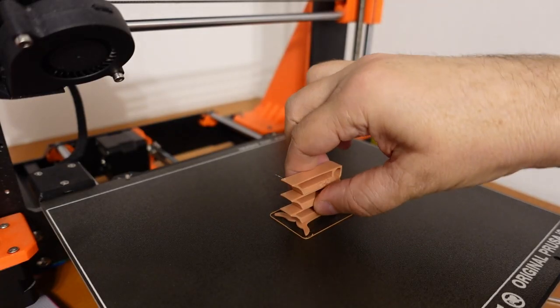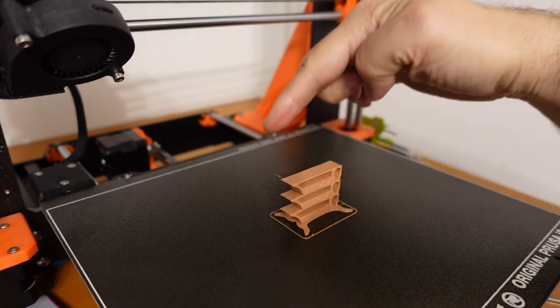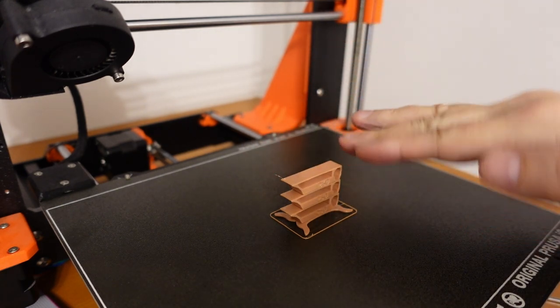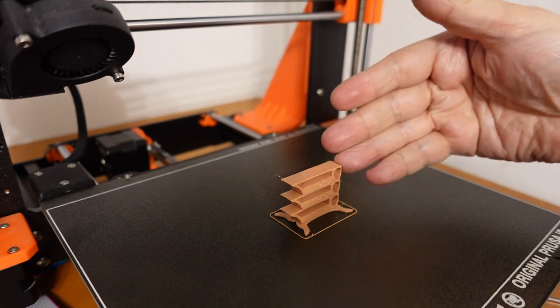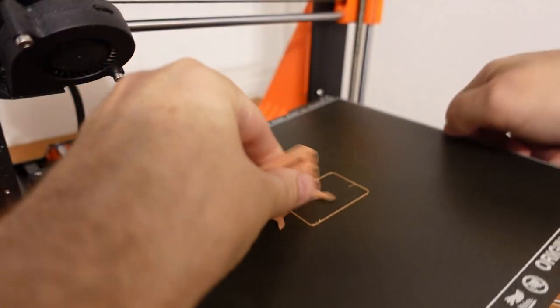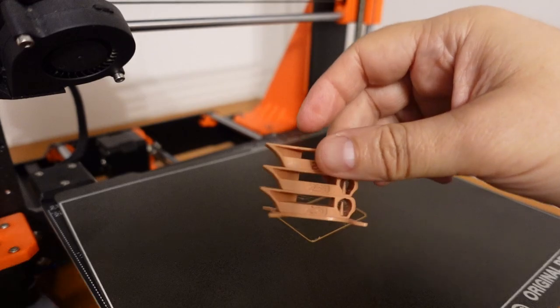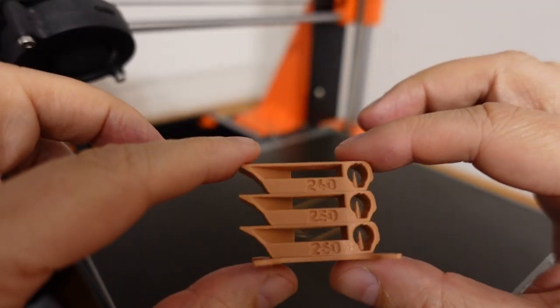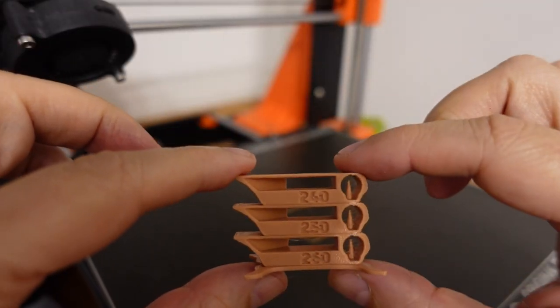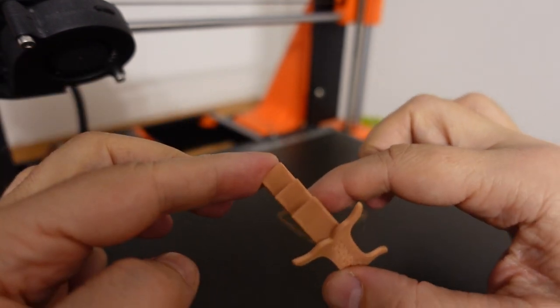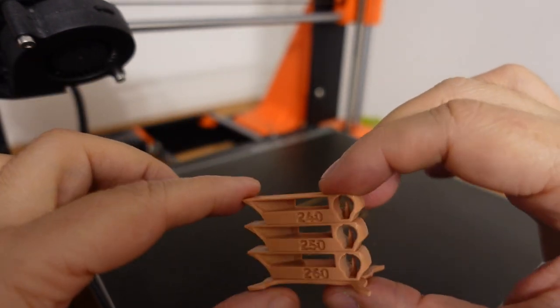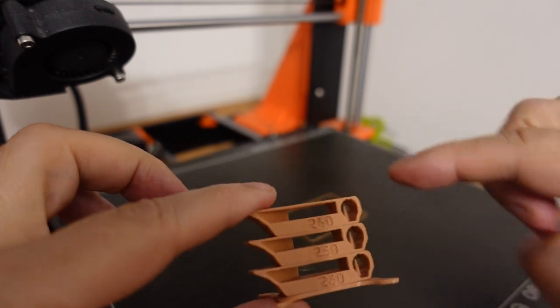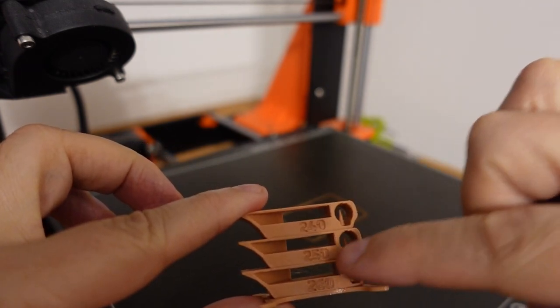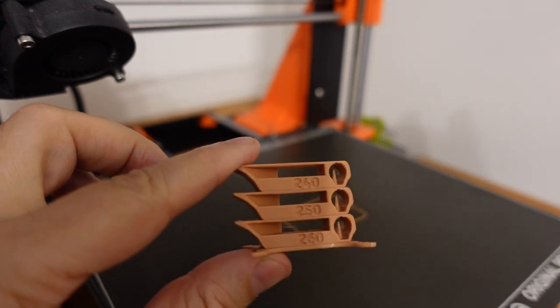The temperature tower is finished, and I know that the adhesion is great with this textured PEI sheet. I have to wait until it cools down and then I can remove it. As you can see, almost no stringing at all, very minimal at 260 degrees Celsius. The overhang is perfect and the bridging. And I can print all test specimens, and they will be printed at 250 degrees Celsius, which is the default inside Prusa Slicer.